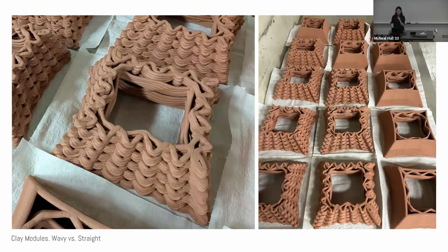We then moved to more complex forms fired from 950 to 1250 degrees. And we speculated initially that the woven forms with more surface area will degrade more quickly than the straight forms fired to the same temperature. And as we do this, we want to document it, right? So, we're all designers. So we are doing image analysis to quantify the material properties and changes to the clay fired to each particular temperature.